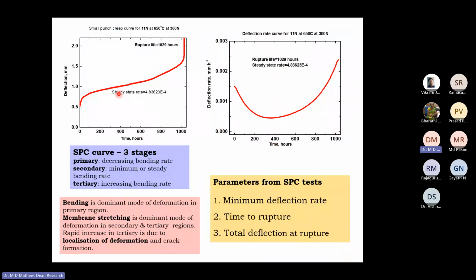So this is a typical SPC curve, deflection versus time. The test has gone close to 1000 hours. You have the typical shape, with the loading strain, the primary, secondary, and tertiary leading to rupture. And you get the deflection rate versus time curve as expected.